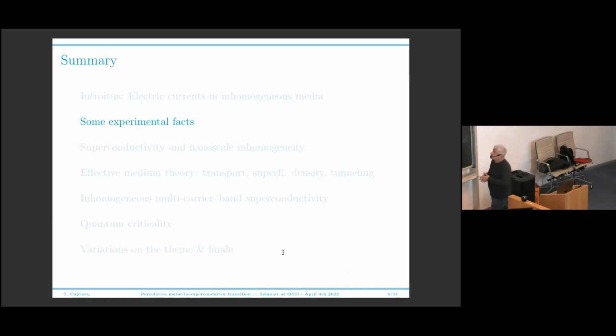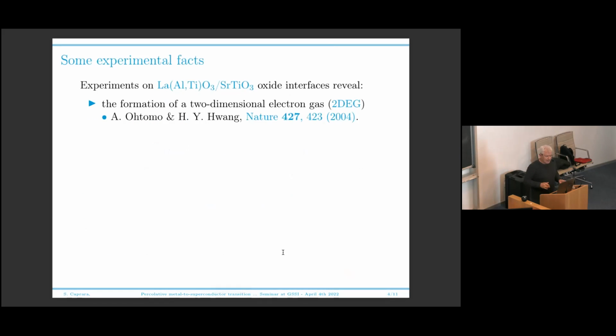Now, after this introduction, I will go through some experimental facts that motivated this research to start with. So let's say, like 15 years ago, some experiments were carried out on oxide interfaces. These oxide interfaces are very curious because you take two oxides, one is strontium titanate, and the other is lanthanum titanate or lanthanum aluminate. Both of these are insulators. You make a sandwich of the two, and then you find out that at the interface between the two insulators, you can form a two-dimensional electron gas.